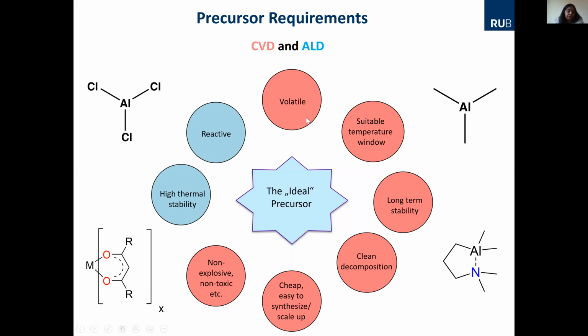In the ideal case, the precursor should be volatile. For CVD, it should have a temperature window. That means it should not decompose at very low temperatures, nor at very high temperatures. So you should have a safe operating window. Then, of course, it should be stable. It should cleanly decompose. For commercial application, it should be cheap to buy or synthesize. For safety issues, it should be non-toxic, non-explosive. And particularly for atomic layer deposition, you need a precursor that is reactive, because as I said, it's a self-terminating reaction with the exchange of the different groups, and thermal stability, because if thermal stability is a weak point, then you may end up with a CVD contribution.